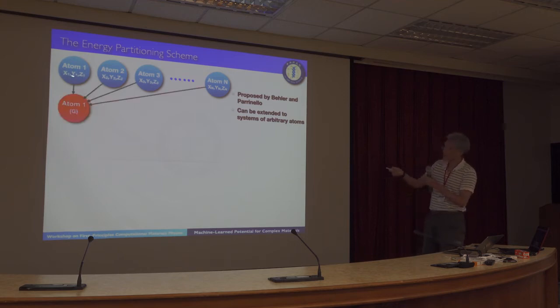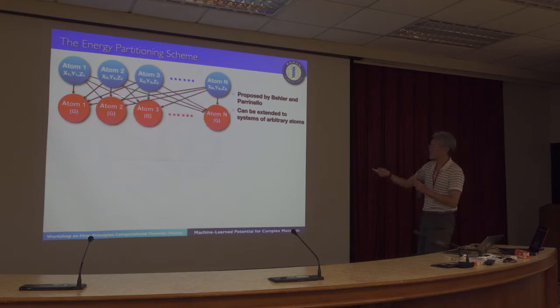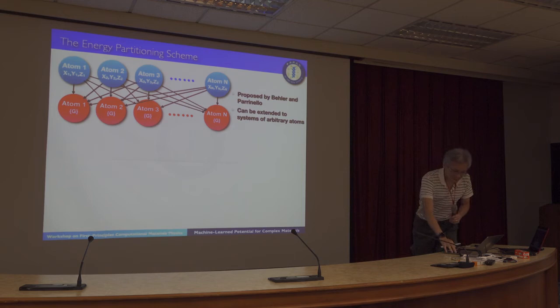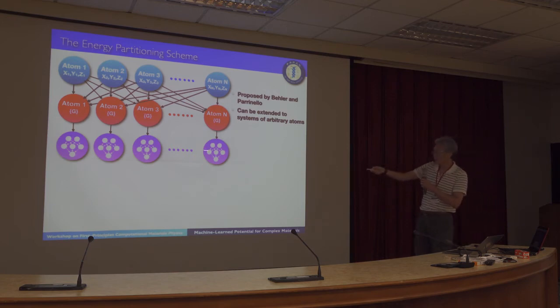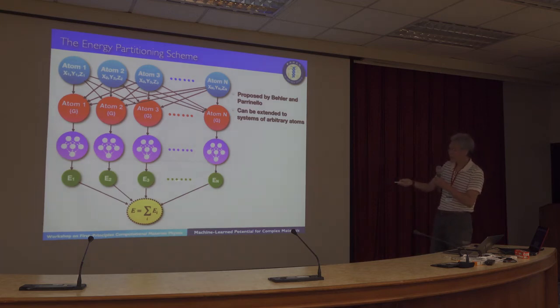So we start from the Cartesian coordinates of the system, and then we convert them into a feature vector for each atom. This basically correlates with the chemical environment of a given atom. Then this feature vector G goes as an input through an atomic neural network. This is why it can be extended to systems of arbitrary size, because the force and energy of each atom is evaluated in its own individual atomic neural network. Finally, we decompose the whole system energy into E1, E2, E3, all the way to En, and the summation gives you the total system energy.